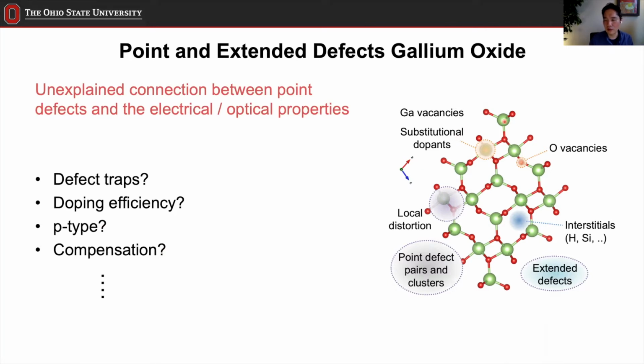When you say point defect, it's a defect at the level of atomic scale, right? If you look at the structure of gallium oxide, you of course have gallium atoms and the oxygen atoms, the red ones. Sometimes you miss these cation or oxygen atoms, which become vacancies, or they can be replaced with substitutional dopants like tin atoms, which I'll show you pretty soon. Those are all different types of defects, right? And then you can also have interstitial defects, like a tin atom being stuck in the interstitial position, or silicon or something else can all go to the interstitial sites.